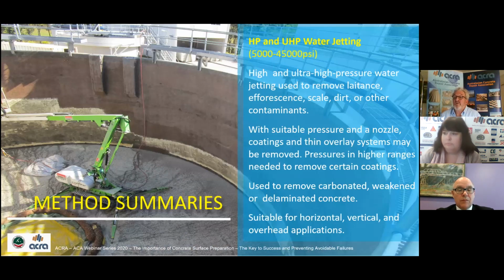High pressure, ultra high pressure water. Now this is generally 5,000 to 45,000 psi. So in other words, it goes from being able to prepare a surface to being able to demolish it. High and ultra high pressure water jetting is used to remove laitance, scale, all of that contamination. With a suitable pressure nozzle, we can get rid of epoxy, urethane, and thin overlay systems. It can also be used to remove carbonated, weakened, delaminated concrete, undesirable concrete from the substrate, suitable for horizontal, vertical and overhead applications.